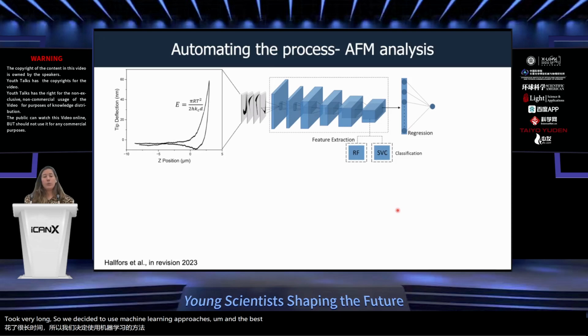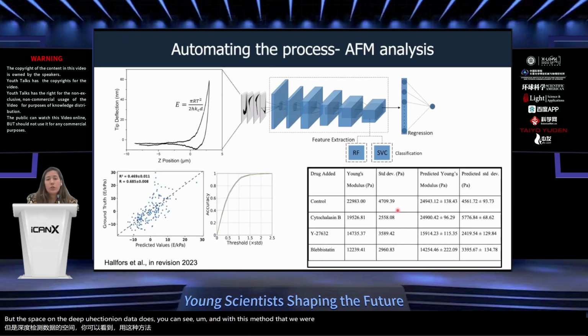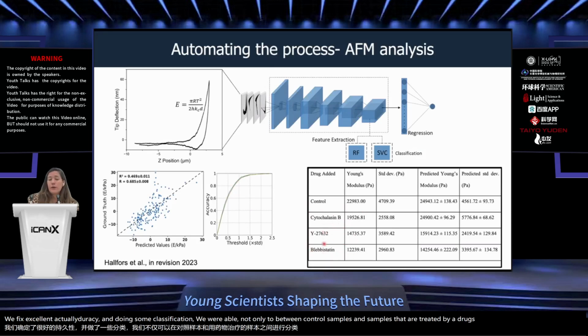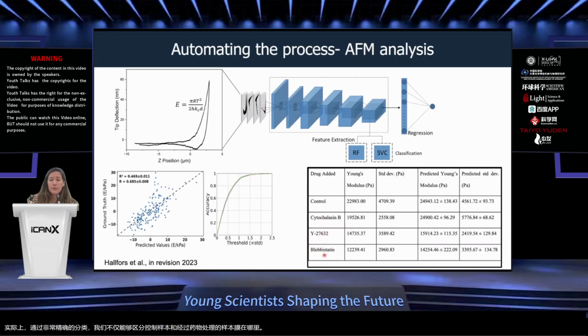And the best way to do that was to use directly the raw data. So the dissipation, the tip deflection data, as you can see. And with this method, we were able actually from the image to extract directly the Young's modulus with excellent accuracy. And doing some classification, we were able not only to differentiate between control samples and samples that are treated by a drug, so that where the membrane has changed its mechanical properties, but also to differentiate between different drugs.